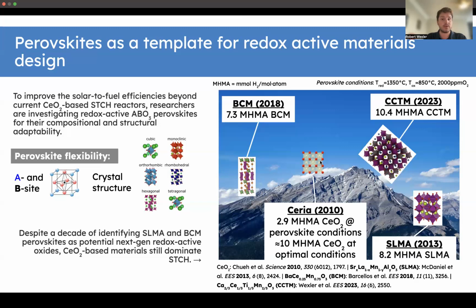Perovskite conditions are the conditions used to test BCM, SLMA, as well as calcium, cerium, titanium, manganese oxide, which is what we've discovered recently, called CCTM. At those conditions, ceria offers 2.9 MHMA. However, at its optimal conditions, at slightly higher reducing temperatures, for example, it offers somewhere around 10 MHMA. SLMA was discovered in 2013. That offers 8.2 MHMA. BCM offers 7.3 MHMA. And more recently, our CCTM offers 10.4 MHMA, which, if you actually look, is better than ceria at its optimal conditions.